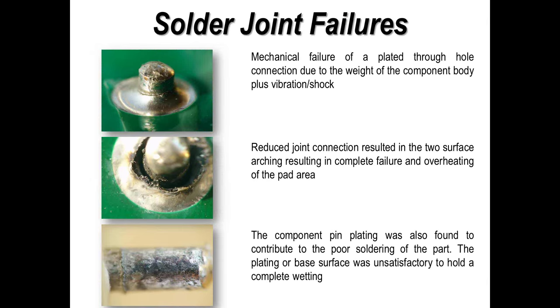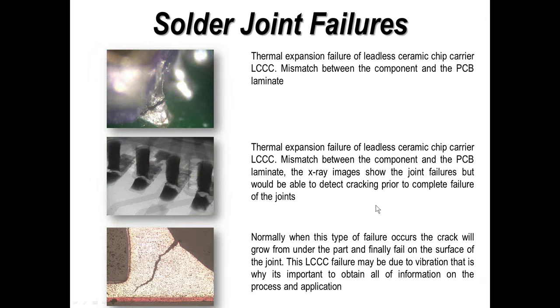So basically, we've got a solder joint, but this was on a very, very heavy component. And basically, what was happening is the product or the board assembly was vibrating, and in time, it actually caused the solder joint to separate. And then at some point, you've got arcing, electrical arcing, which actually caused the joint plus the board to start to overheat and then burn. Now, if we look at the component termination and look at the pin and then looking at the application, we should have been able to figure this out, what the root cause of the problem was. But it's looking at each surface. Everybody, well, a lot of people tend to concentrate on one surface, but always look at both surfaces. That gives you a good indication of the potential failure mode.